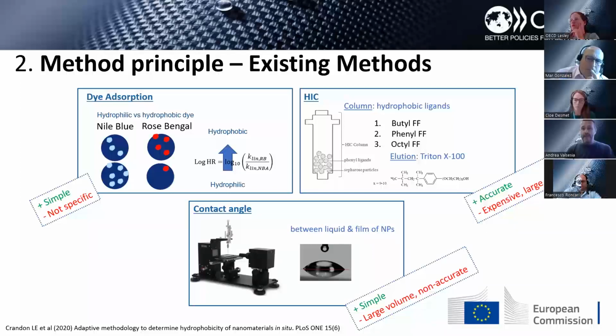The second method is based on column chromatography. You have three different materials in the column, which increase in degree of hydrophobicity. Then you pass your nanomaterial through the column using an elution agent, and you measure the affinity of the nanomaterial to the column. Actually, this method is relatively similar to what we are doing in our method. It is really accurate because it measures the affinity of the nanomaterial to the hydrophobic column, but it has the big disadvantage of being really expensive, because the column costs quite a few hundred euros for the three different chemicals, and you also need a large volume of your nanomaterial, which is not always the case.